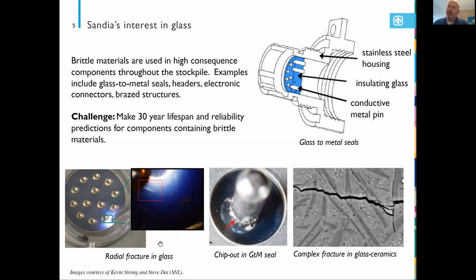Another failure mode for this type of seal is shown in the center here. This is a half moon chip out that is localized about the pin, and how this might have occurred is maybe a deflection in the pin, which ultimately gives rise to a failure within the glassy material. But once again, this would be a failure situation. And as I had brought up before, often they use glass ceramics and not just glasses. They sometimes choose glass ceramics because they are stronger.